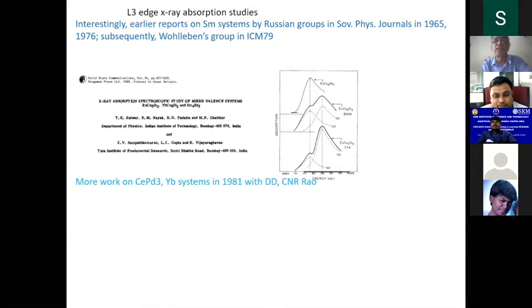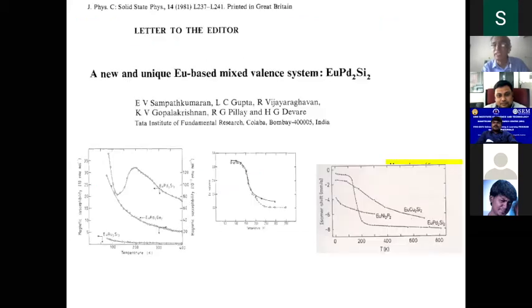Okay, this is again X-ray absorption spectroscopy. Unlike electron photoelectron spectroscopy, the X-ray absorption spectroscopy core level is more bulk sensitive. In one of the very first papers in this field which we published, if you have two valence states, you see two peaks here. If you have one valence state, one peak here. You can derive the valency value by decomposing these curves. So this technique was considered a very ideal technique even compared to electron spectroscopy because it is more bulk sensitive, less surface sensitive.